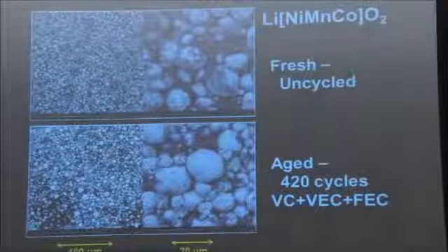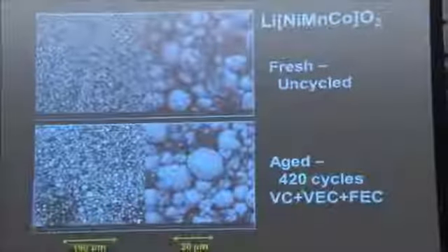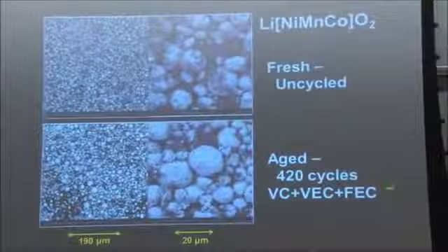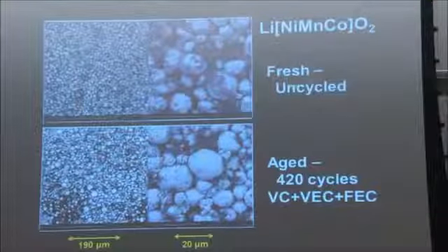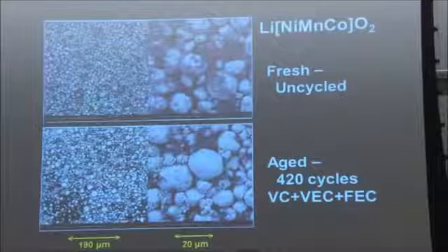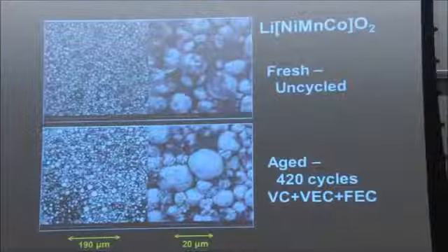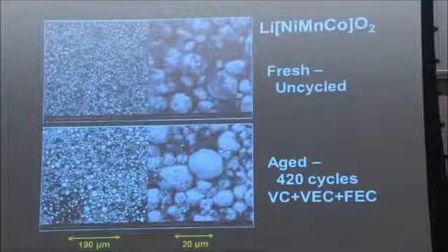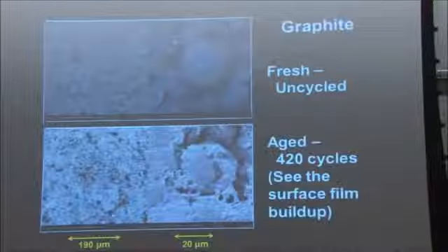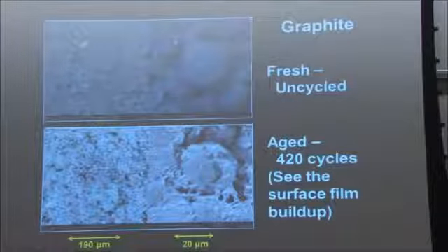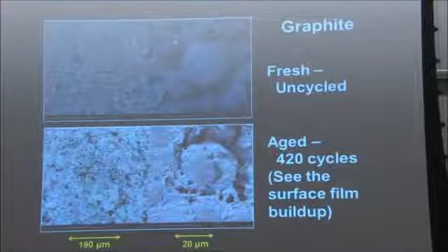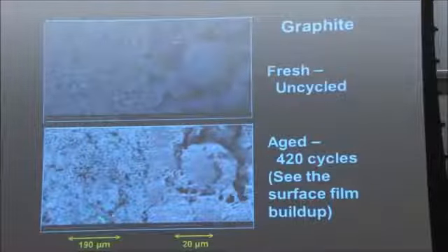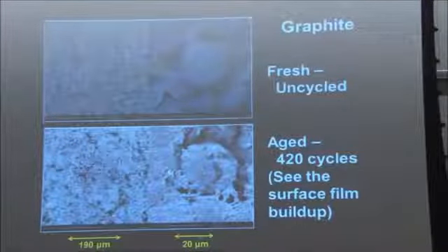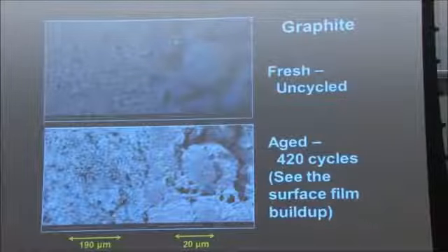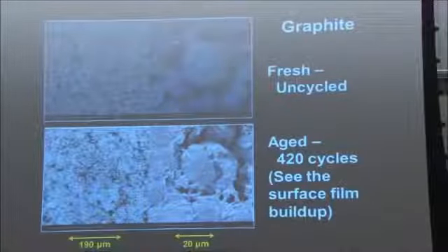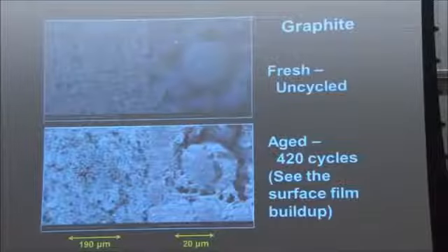And if you look at the positive electrode by SEM, I just picked one of the cells with VC, VEC, and FEC. After 420 cycles, it failed. Before the cycling and after the cycling, positive electrode looks exactly the same. And if you look at the negative electrode before and after, you can see the buildup of this film of reaction products on the surface of the negative. So this square region has been expanded over here, and you see all this gunk on the surface of the negative. And that's what's leading to the failure of the cell.